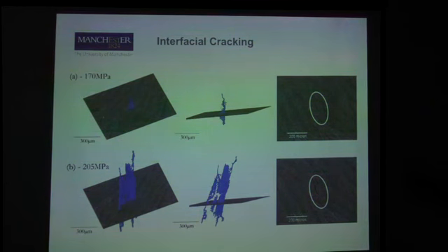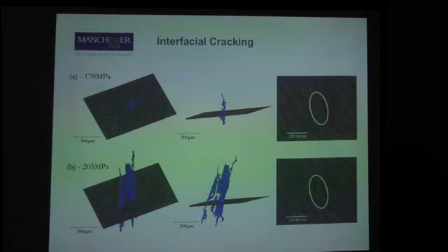Okay, and then just the final thing is the interfacial cracking. And obviously, these cracks, like I said before, this is a mode 2 type of crack formation. These are obviously different. These are much broader, and like I say, are just simply running along the metal ceramic interface in mode 2. Again, not initiating from cracks in the ceramic lamellae. Again, this is two modes of failure that are occurring simultaneously.